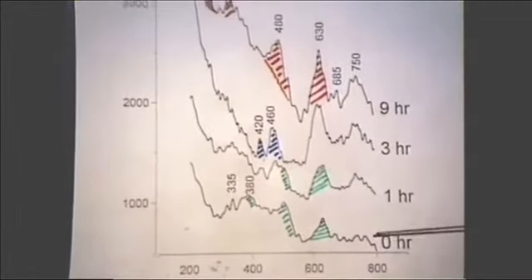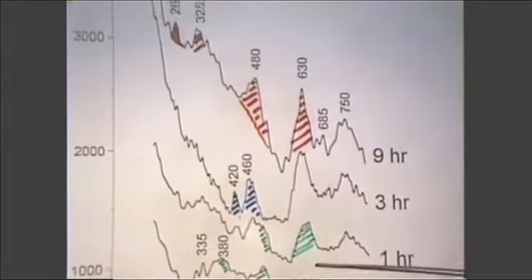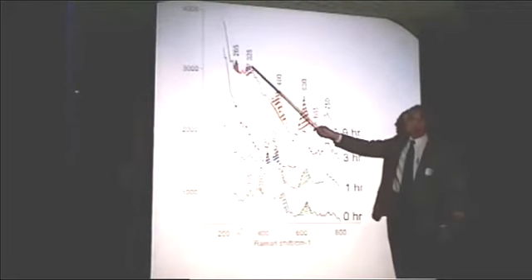So what we see here is a progression of time of the sulfated zirconia being oxidized at 500 degrees C. And this spectrum here is representative of the monoclinic form of zirconia. As we heat the catalyst, we ultimately go through some transition forms, which don't seem to correspond to any crystalline phase of zirconia that we know of, but we ultimately end up, at least with the right number of peaks, and even these two peaks down here, which are quite diagnostic of the tetragonal form of zirconia. So it appears as though oxidation can transform the zirconia from the inactive monoclinic phase to the active tetragonal phase, the sulfated zirconia.